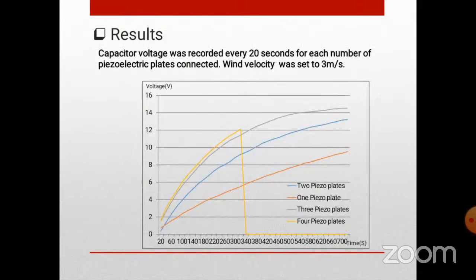These are the results observed during the test. First, only one piezoelectric plate is tested and then more are added one by one to measure the voltage gain. As you see, when the number of parallel piezoelectric elements increases, the time taken to charge the capacitor decreases. Wind velocity is set to 3 meters per second artificially for testing purposes. With 3 piezoelectric plates, the voltage rises up to 14.2 within 600 seconds.